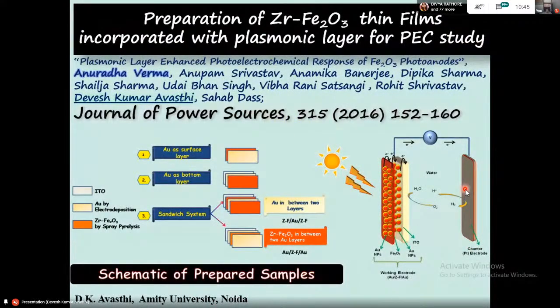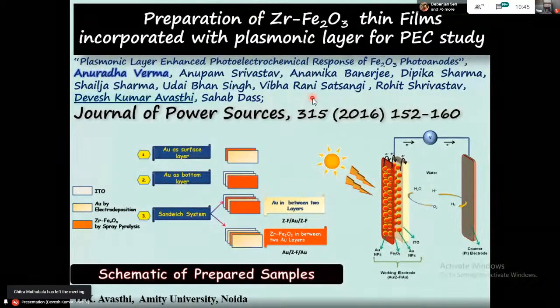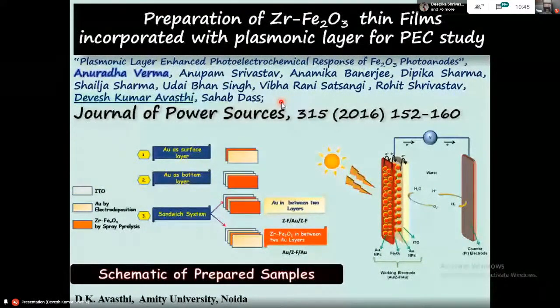So here is the work which is in collaboration with Dr. Sahab Das from the Dayalbagh Institute in Agra, and they are working in this area. I had suggested that they should use gold as a surface layer, or a bottom layer, or a sandwich layer and try this. And this is what they tried, and we have a common student, and we have very encouraging results. Whether we use it just on a top layer of iron oxide, or as a bottom layer, or sandwiched in between,